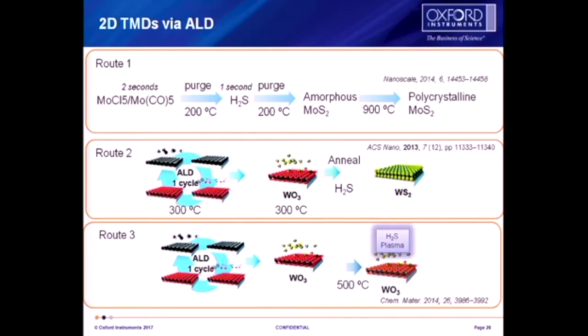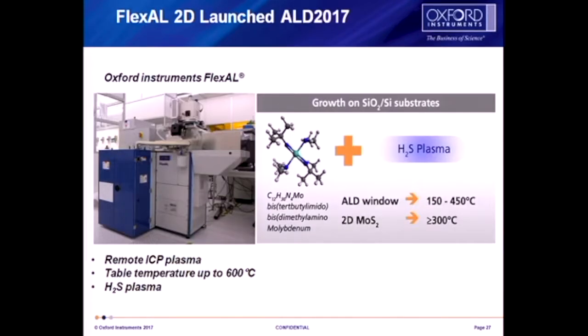But our collaborators at Eindhoven at ALD 2017 presented a paper on doing actual ALD of molybdenum disulfide, which is crystalline. This is the ALD FlexAL tool that they did the work on. You can see we've got an ALD window of around 150 to 450 degrees C, and we see 2D crystalline molybdenum disulfide at greater than 300 degrees C.